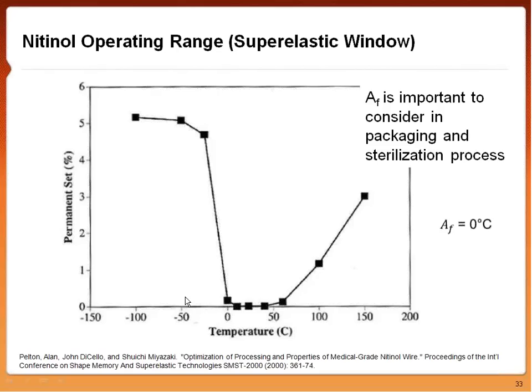But if you think about it, based on those earlier curves, by shifting your AF, you can shift how stiff your device is. When you shift your AF, you also shift this window. So if you imagine a customer says, okay, I want an AF of maybe minus 20 degrees because I want a super stiff stent, you're going to shift that window down, and you might actually hurt your device when you go to sterilize it, which isn't good. So you're going to have permanent set in your device when you go to sterilize it.